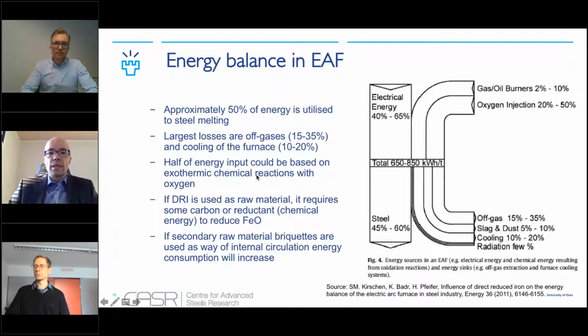And if we look at the input, we see that half of the energy could be based on the exothermic chemical reactions with oxygen. If we are using DRI as a raw material, it means that we will need some more carbon or reductant to reduce FeO, which is partly in DRI. And if secondary raw material briquettes are used in electric arc furnace as a way of internal recirculation, then energy consumption will increase as well.